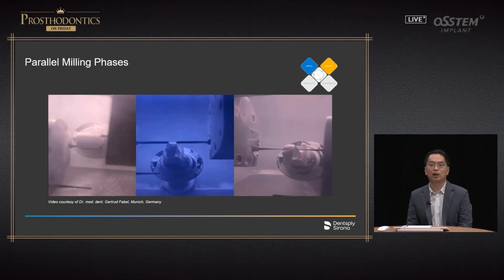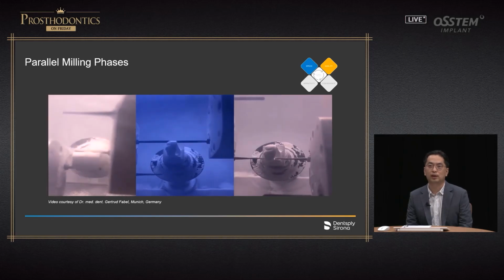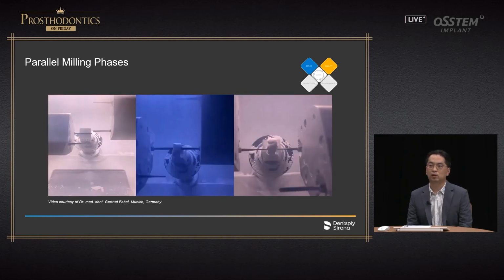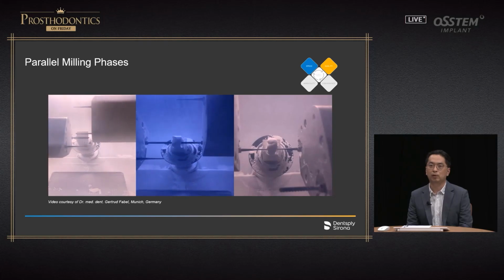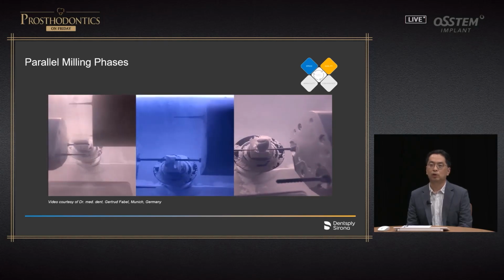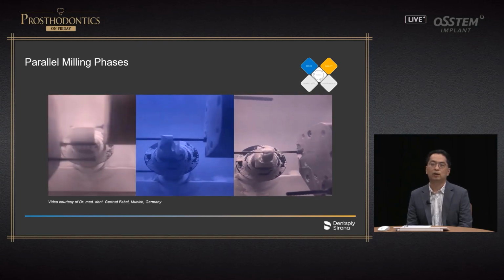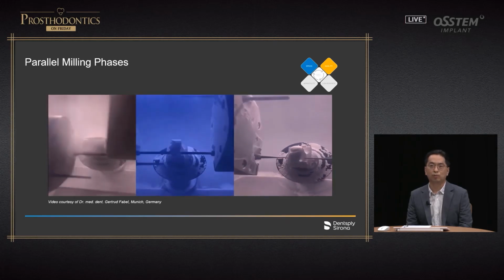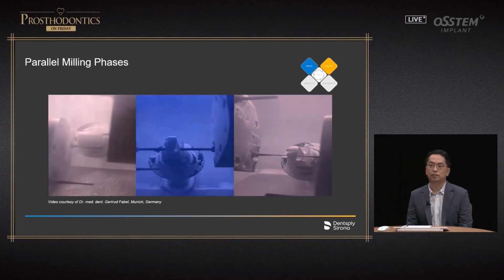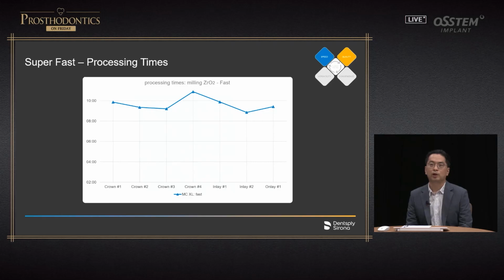Of course, this will lead to reduced milling time. Parallel milling is only possible with a machine known as PrograMill. If you fabricate a prosthesis like this, milling time can be significantly reduced. In the past, milling a crown took about 10 minutes. However, if you do parallel milling, the milling time is reduced to 4 minutes or 6 minutes.